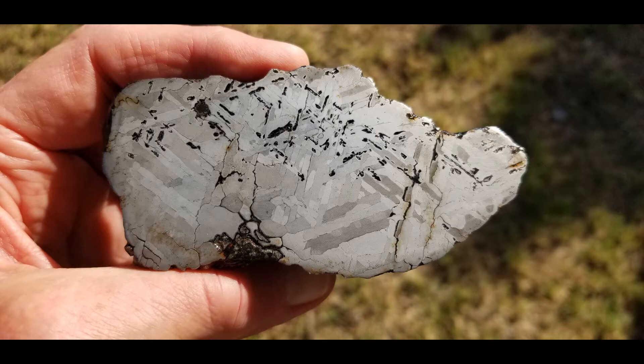Once I took a hard look at it, I noticed some rust spots still evident. The first one I saw was up in the left-hand corner. There's another one in those two grains right there — hard to see but it's there. There's one on the tip down there, and down on the bottom there's quite a bit, and there's a little tiny dot right there. These have to be dealt with; otherwise, if I just coat this, they'll be trapped inside and eat the meteorite away from the inside.